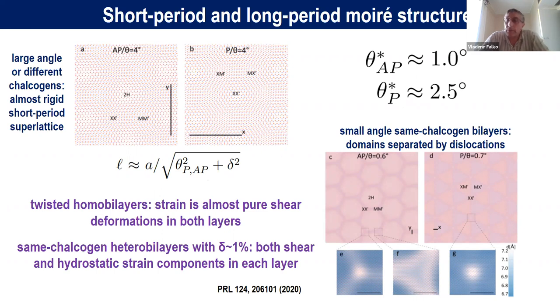So on the right-hand side at the bottom, we have examples of what we get if we take this angle very small. For anti-parallel configuration of the unit cells of the two crystals, the domains that form are 2H stacking domains. That's where the chalcogens are above metals and metals are above chalcogens in both layers. And the domain walls that separate them have a network structure with corners, which are different. There are three corners where the chalcogens are on top of each other, and three other corners where the metals are on top of each other. This is energetically not so bad for the bilayer structure, and that is why these corners are kind of swelled. They are actually small seeds of MM prime stacking with the size of several nanometers.